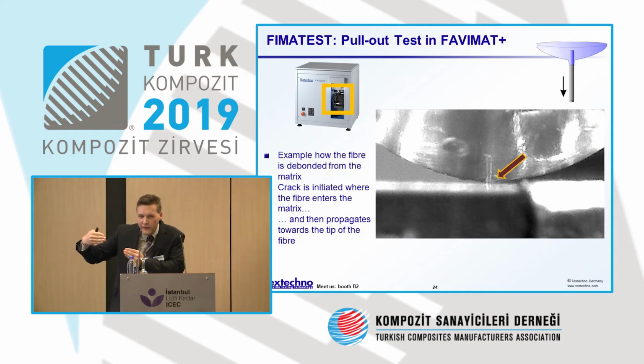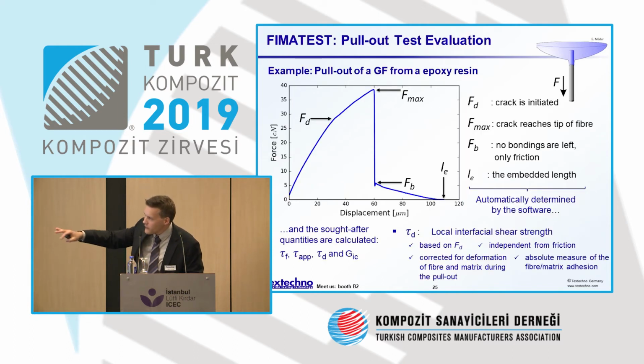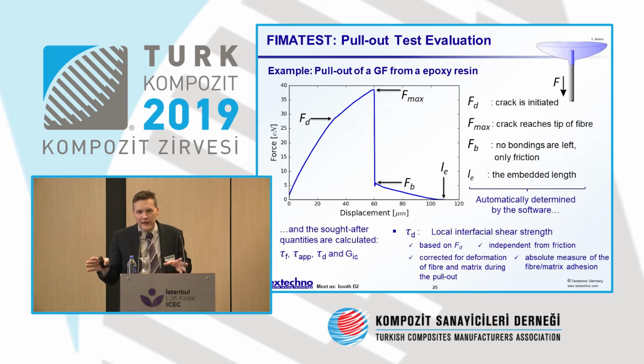And the really interesting thing is that we are able, with this test system, to identify the force where this initial crack is forming, because that's just the force or the stress where the bonds are really being loosened. And that's the power of this microscopic testing technique of single fiber pull-out testing. Here's what the force displacement curves look like. I'm not going to go too much into detail at this, but the important thing is that it's a very clean measure of fiber matrix adhesion on its own in terms of local interfacial shear strength, and it's corrected for all the complicated deformations that go on otherwise in such a test.